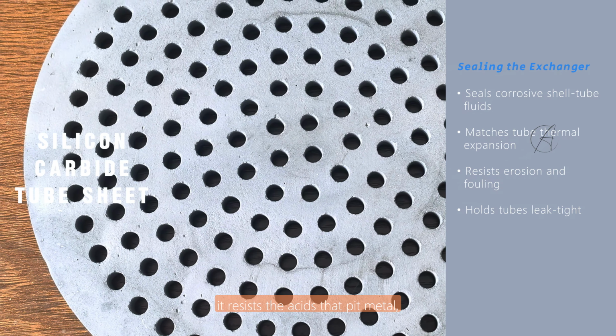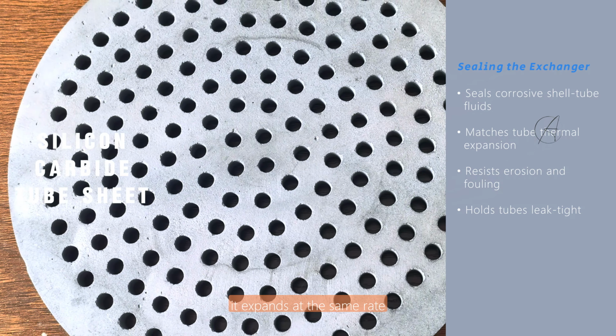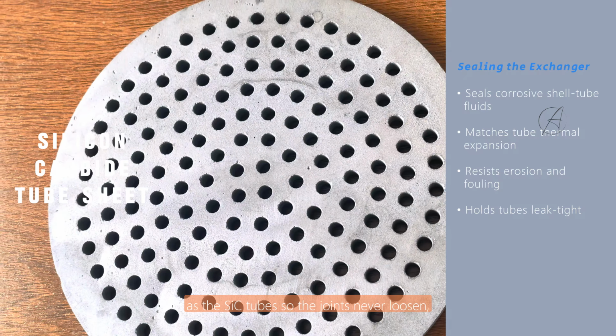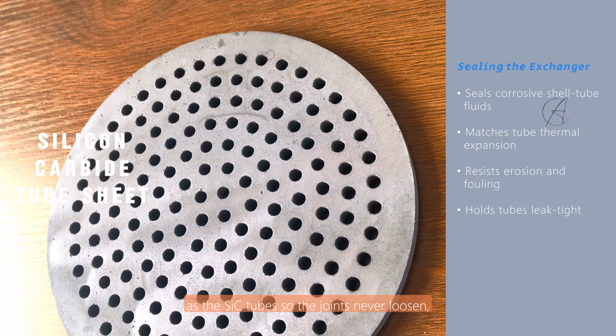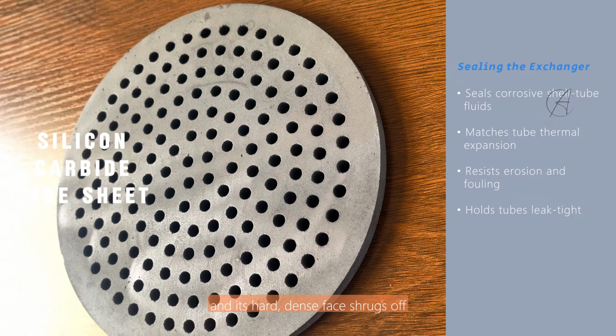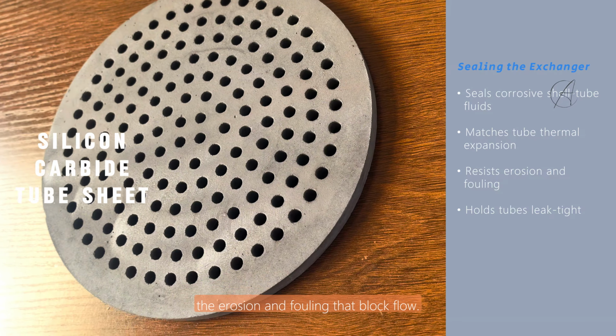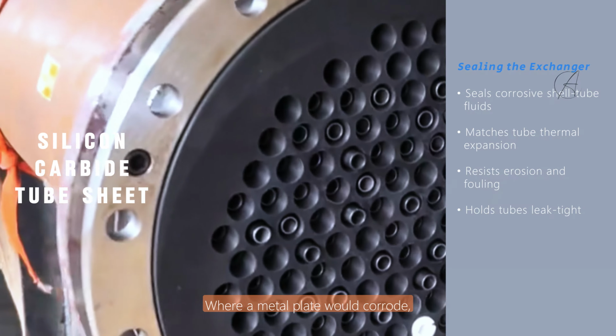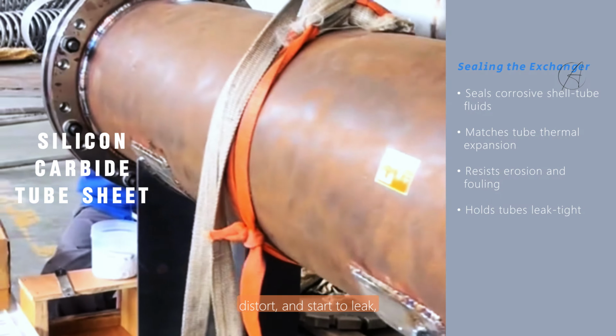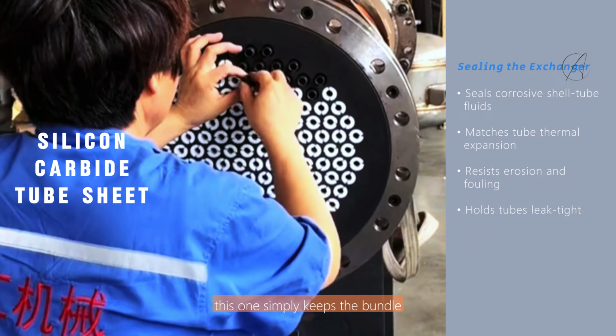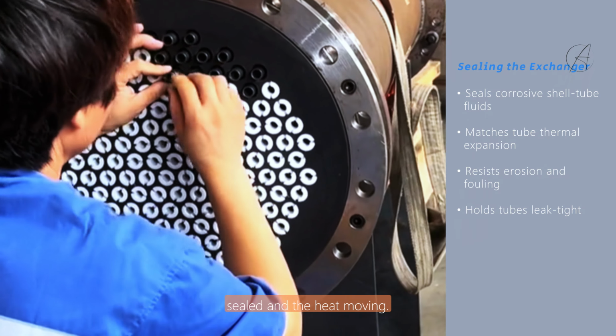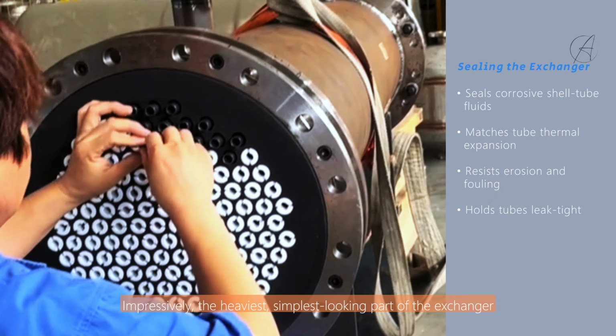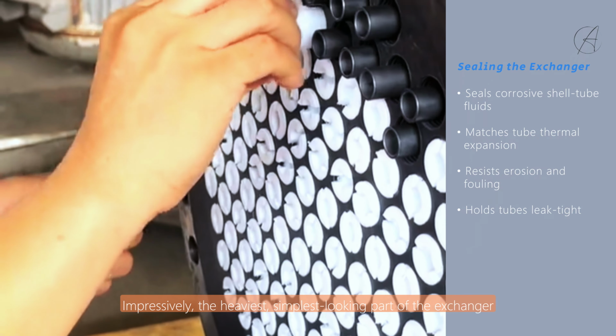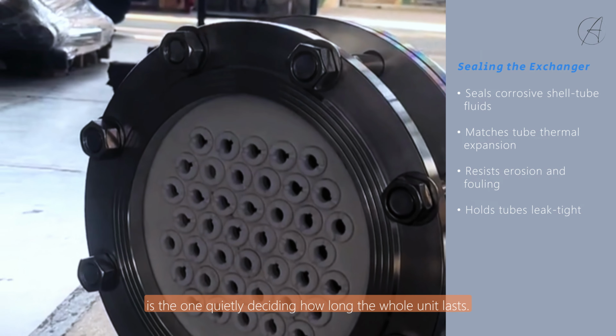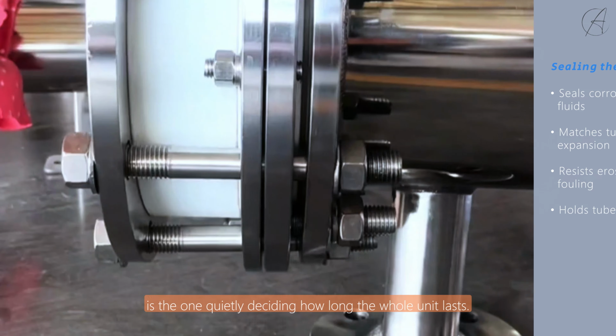It resists the acids that pit metal, it expands at the same rate as the silicon carbide tubes so the joints never loosen, and its hard, dense face shrugs off the erosion and fouling that block flow. Where a metal plate would corrode, distort, and start to leak, this one simply keeps the bundle sealed and the heat moving. Impressively, the heaviest, simplest looking part of the exchanger is the one quietly deciding how long the whole unit lasts.